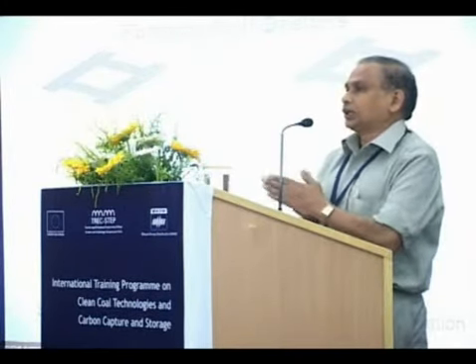A once-through supercritical boiler can operate both at supercritical pressure as well as subcritical pressure. That is, when you operate at 100% load, it will be operating at supercritical pressure. When you operate at 80% load, it will be operating at supercritical pressure, that is about 221 bar. But when you come down below 80%, the same boiler will act as a subcritical boiler, because the pressure comes below the 221 bar limit. So, these boilers are suitable for both subcritical and supercritical pressure. A once-through boiler can be used for both subcritical and supercritical, whereas a drum boiler cannot be used for supercritical pressure. This is the basic difference.